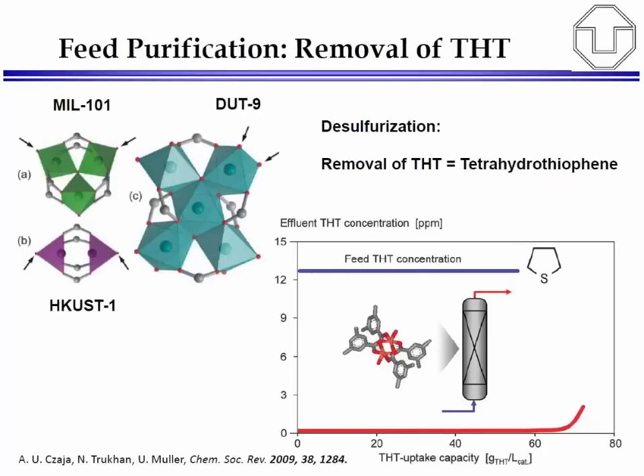Very early on, and this is on the next slide, thank you, it was already shown that MOFs can be used also for trace gas removal, trace impurity removal. For example, in gasoline or in general in feeds, often sulfur compounds are a problem for catalysts. And some of the MOFs have very high affinity towards sulfur compounds because they have these active metal sites, for example in HKUST-1 or MIL-101. And on the right-hand side, this is from Müller's publication from BASF, showing that you can achieve a very good removal for example, for model thiols, tetrahydrothiophene, which can be removed quite efficiently. And I think this is also one of the strengths of the metal organic frameworks, that they can be used for selective removal of certain toxic or not wanted gases in a gas stream.